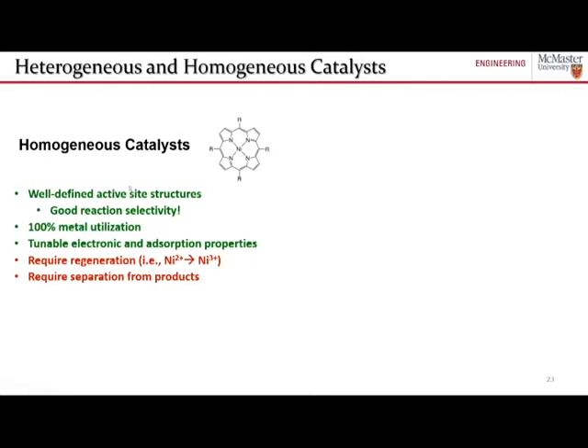Some of the challenges of homogeneous catalysts, one is that oftentimes they require regeneration, so either reoxidation or re-reduction to whatever their active oxidation state is. So a lot of times they're running a liquid with a solid electrolyte in there that they need to absorb upon, be regenerated, and then they become active again. And another problem is that, as I mentioned, they are in the same phase as the reacting species, which means that a lot of times separating the catalyst out from the products can be a challenge when dealing with homogeneous catalysts.